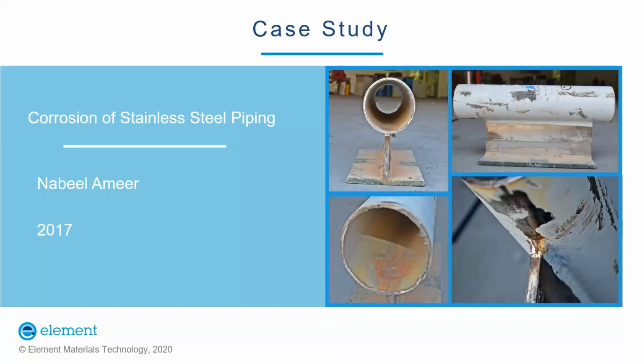The piping system was hydro tested for a period of 2 days. Potable water was used during the test. After the hydro test, the piping system was dried. During the pre-commissioning stage of the project, exactly after 2 months of hydro testing, various leaks in the piping systems were detected at different locations. Material of construction was 304 stainless steel, which is a general purpose stainless steel with adequate corrosion resistance.